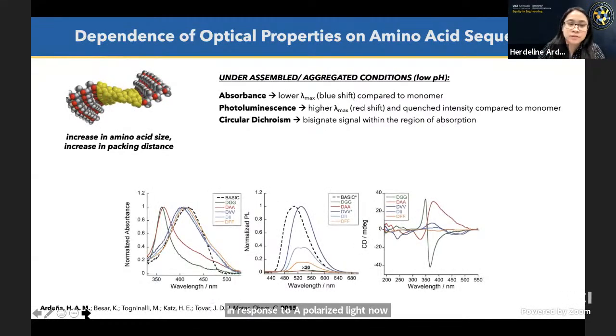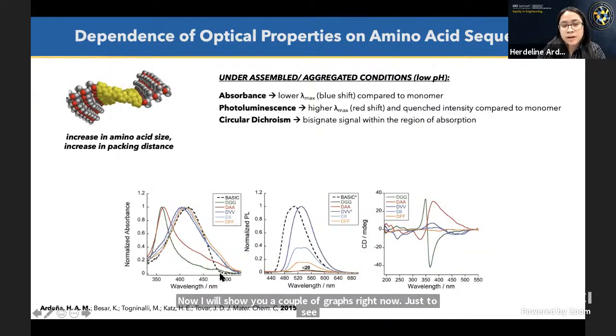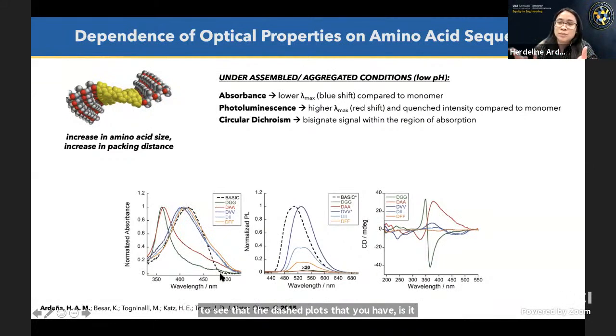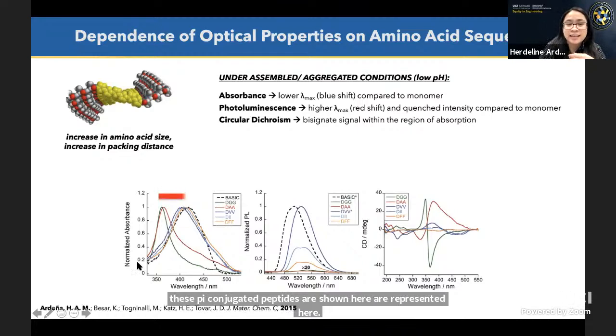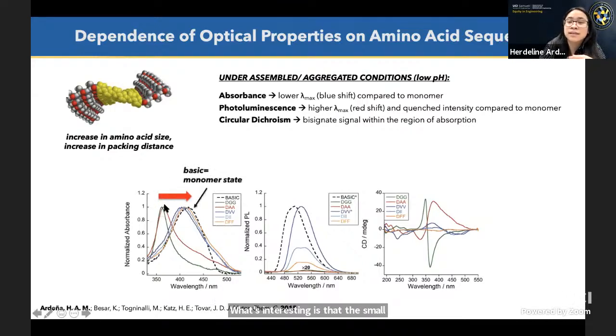Now, I will show you a couple of graphs, just to see that the dashed plots are equivalent to the monomer, representing the optical property of the monomer. And then the profiles for the different amino acid modifications for these pi conjugated peptides are represented here. What's interesting is that the smaller amino acids are significantly different from the peptides with the larger amino acids, and we can actually see a trend starting from the absorbance profile.